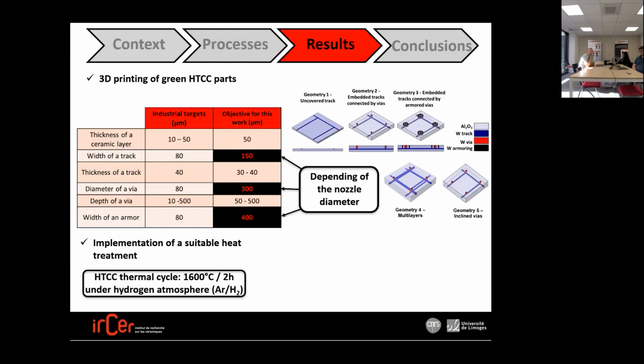So, results. First, we have to print 3D parts, 3D green parts. Here you have a table with the industrial target for the HTCC part and the objective we have been able to reach during these two PhD theses. The cells in black are directly linked to the nozzle diameter used for the deposition process. Second, we have developed an HTCC thermal cycle, which is able to co-fire the printing and obtain good mechanical and dielectric characteristics. The atmosphere must be a hydrogen and argon atmosphere.